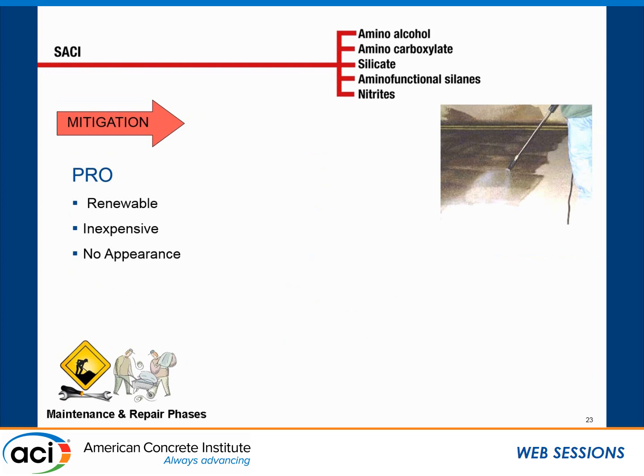Surface applied corrosion inhibitors, a very controversial topic. They're renewable, fairly inexpensive, they don't really change the appearance, and they're easy to apply. It works by magic. They're inhibiting, they're not solving the problem. They may slow it down, they may not. Your choice is, if I have a lot of corrosion going on and I use one of these, it's easier to apply than ripping out the concrete and doing more invasive procedures. It may help. It may not.